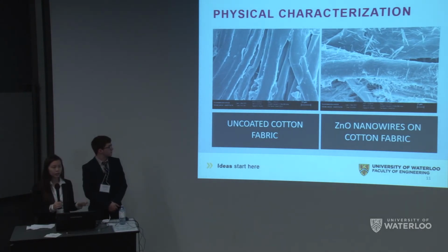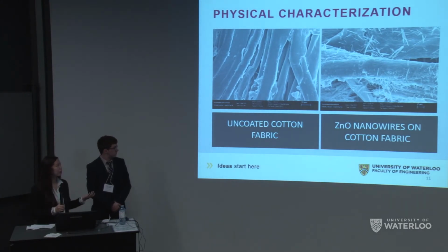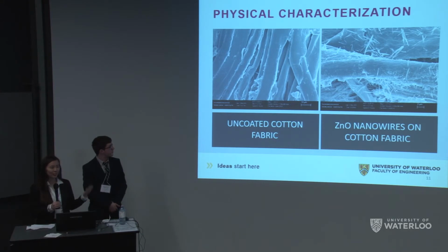We performed physical characterization after we coated using SEM, and you can see that there's actually a significant amount of nanowires deposited on our cotton, which is good because it shows that it actually stuck to our cotton and didn't just fall off. But the nanowires are notably unaligned and they're actually clumped together. We were hoping to achieve a more even dispersion.